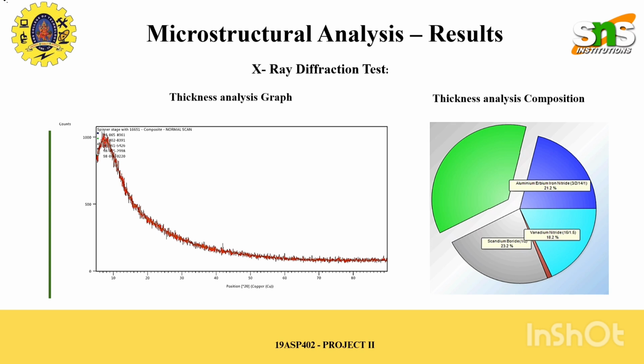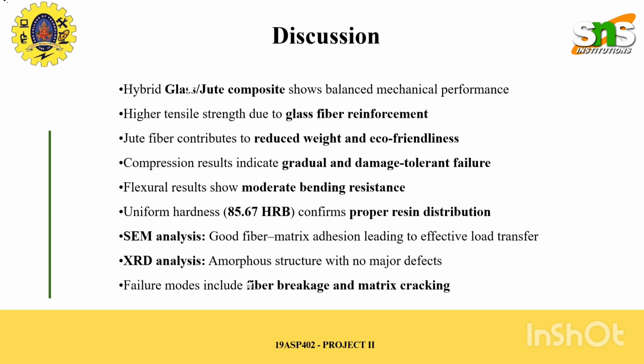From the overall discussion, it is observed that the hybrid glass and jute composite exhibits balanced mechanical performance. The presence of glass fiber enhances tensile strength, while jute fiber contributes to reduced weight and eco-friendliness. The compression and flexural results show stable and damage-tolerant behavior.